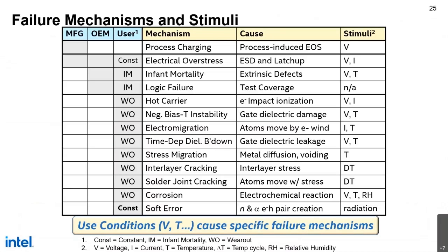So any one silicon and one package has essentially all of these that are considered, and in all of the use areas. So we look at the IM, we look at extrinsic defects, we look at the wear out. So these are all of like hot carrier or solder joint cracking or interlayer cracking. And in the constant area, there's the soft error, right? So we're able to consider all of these in design and in simulation.